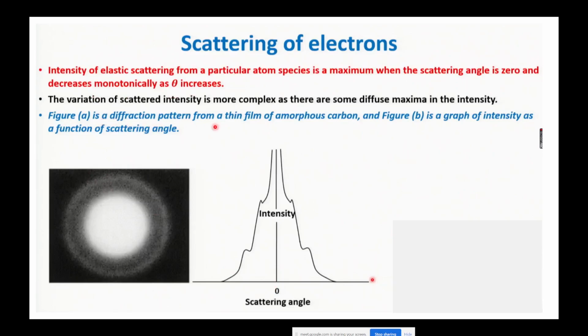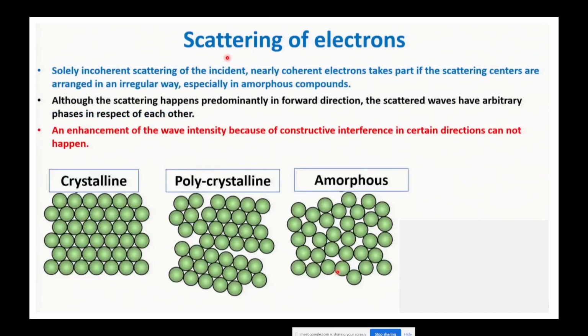Now, this is a diffraction pattern from a thin film of amorphous carbon, and B is a graph of intensity. So this is the diffraction pattern you will get, and this is your intensity as a function of scattering. This is incoherent scattering of the incident, nearly coherent electrons. It takes part if the scattering centers are arranged in an irregular way, especially in an amorphous material. This is your amorphous material, where your atoms are randomly oriented, not in a very specific manner.